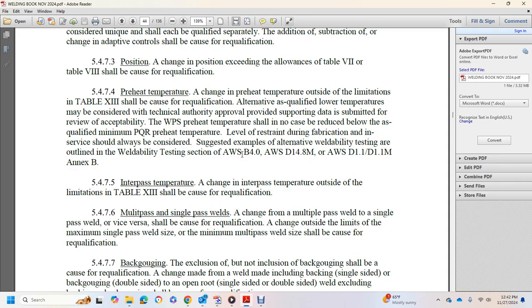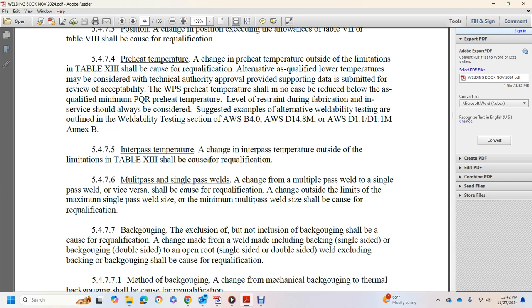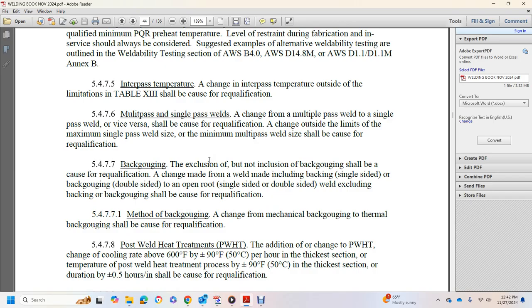Multi-pass and single-pass welds: a change from a multi-pass weld to a single weld pass, or vice versa, should call for requalification. A change outside of the limit on maximum single-pass weld size or maximum and minimum multi-pass welding symbol size shall call for requalification. Back gouging: the exclusion, but not the inclusion, of back gouging should be covered by the requalification. Welds made including back gouging, single side with back gouging, double side, open root single side and double side, and welds excluding back gouging are covered by requalification. Back gouging by mechanical or thermal methods is covered by requalification.